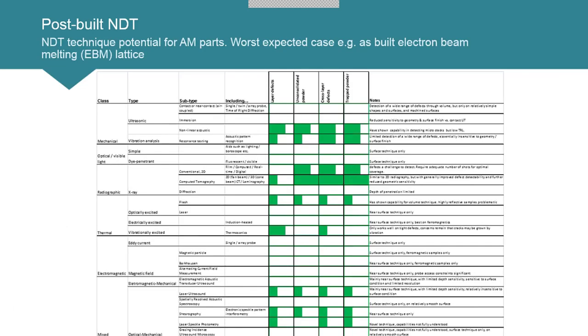Apologies for the size, I don't know if you can read that. I just could not fit it all in here, but this is something that will be included in the standards, and this is a table showing the potential of NDT methods for each of those unique additive manufacture defects. The size of that green bar is the estimated potential for detecting that particular defect using a particular NDT method. Now, we made this an estimate, where we could actually modify the roughness of the sample. In this case, it is the worst case.